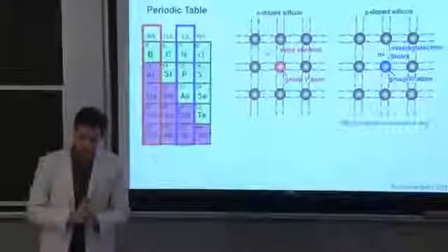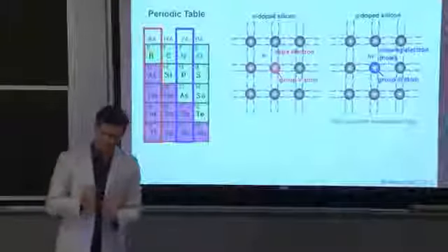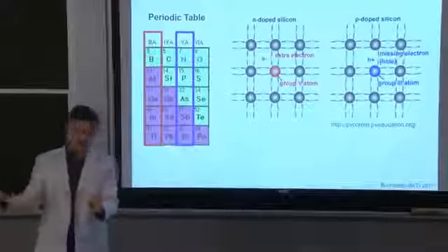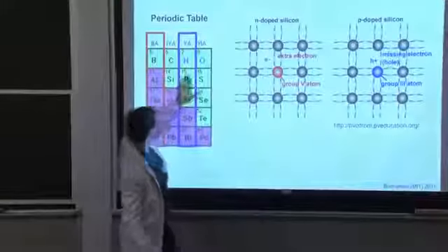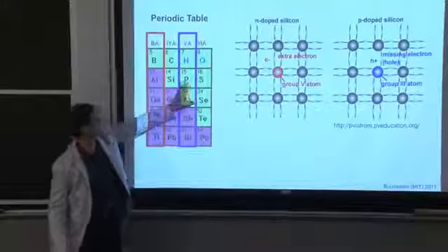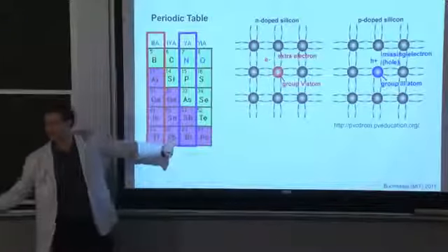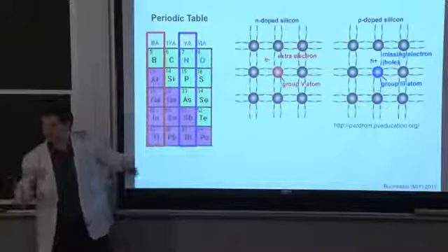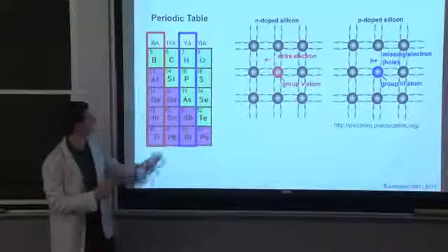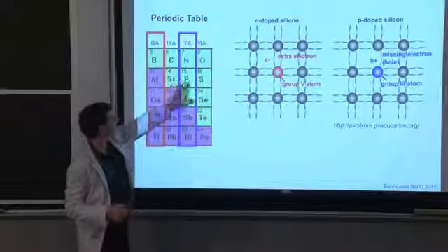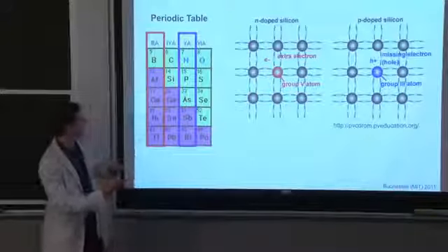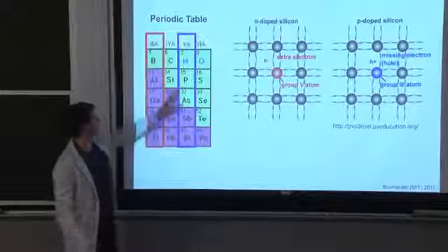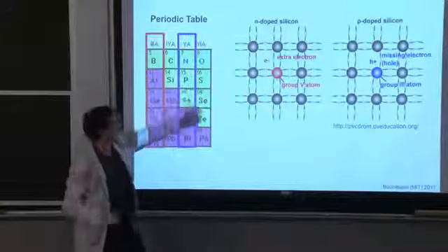So you can envision that if you were to introduce an atom and substitute out one silicon atom in that lattice for something else that has 5 valence electrons, such as phosphorus, right? It's almost of equivalent size. So those materials scientists in the room, from the Hume-Rothery rules, you should be able to estimate that the miscibility is rather large. In other words, you could mix in a high concentration of phosphorus into your silicon, given the similar size and similar atomic structure, electronic structure, rather.